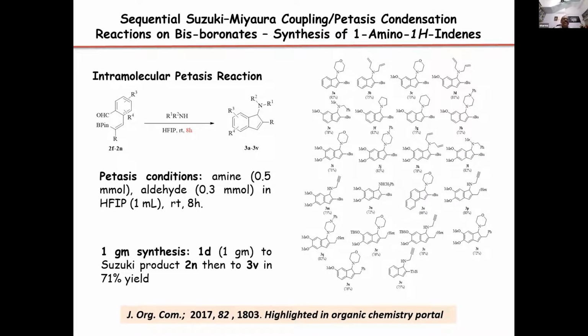Yeah. These systems are subjected to intramolecular Petasis reaction in the presence of amines and hexafluoroisopropanol solvent at room temperature. Nicely, successfully, they gave the 1-amino 1H-indenes with excellent yields. The reaction went very well at room temperature in 8 hours of time. This method was adaptable even for 1 gram scale. We have used the bisboronate 1D to convert it into Suzuki product 2N, which then was subjected to intramolecular Petasis reaction to give indene 3V in 71% yield. Next, please.